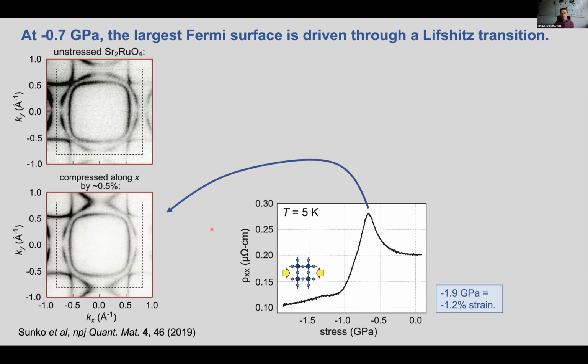So this Lifshitz transition here corresponds to the peak in resistivity. So here's resistivity data now going to very high stresses, about 2 GPa, and we can see, again, this very strong decrease in resistivity that saturates, brings the resistivity down to about half of its unstressed value.